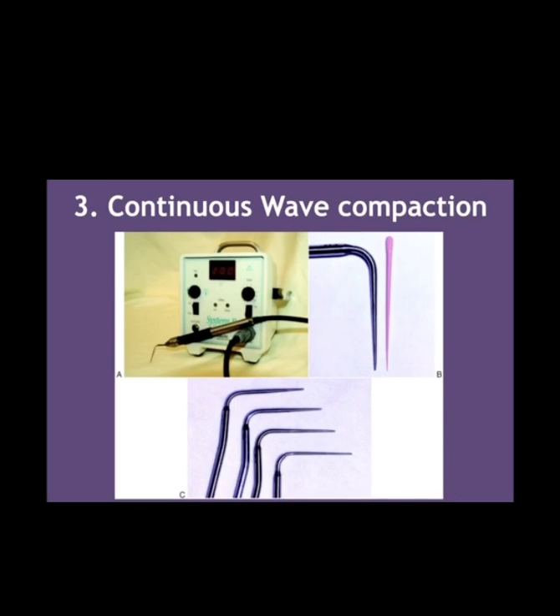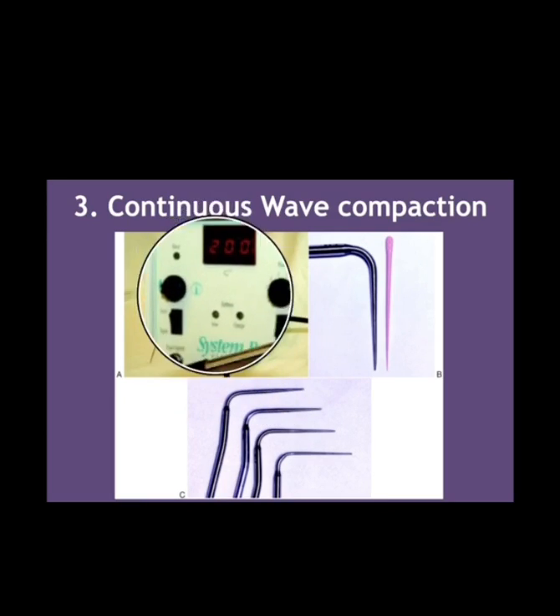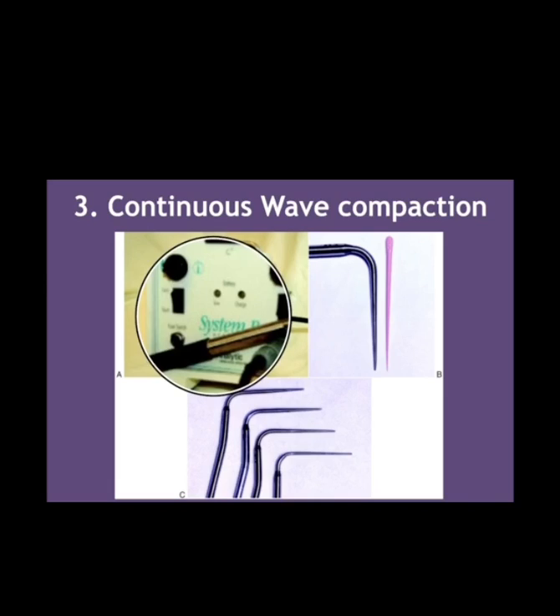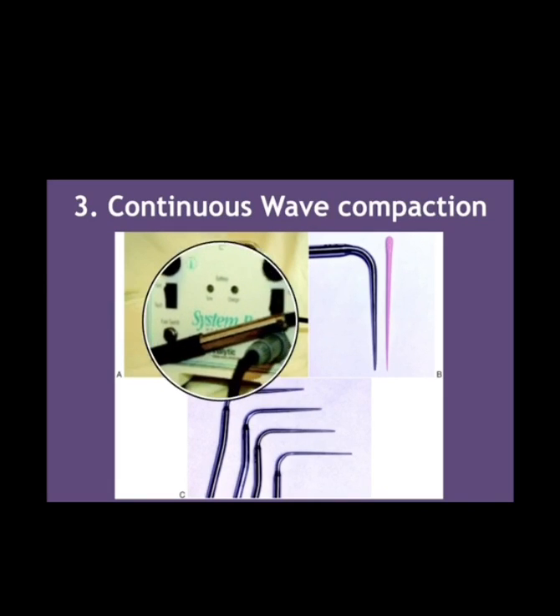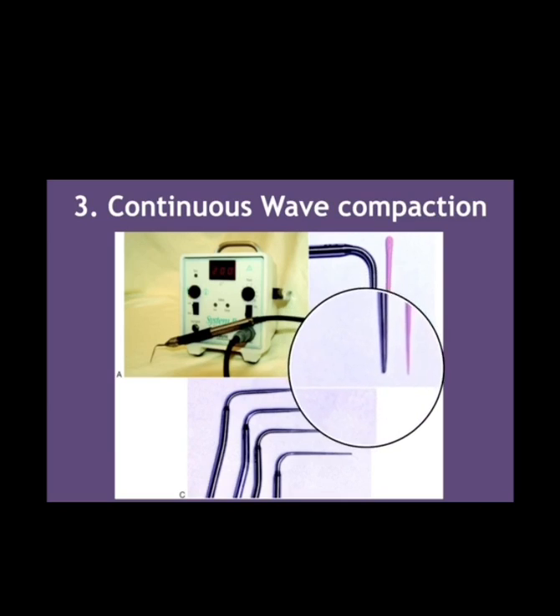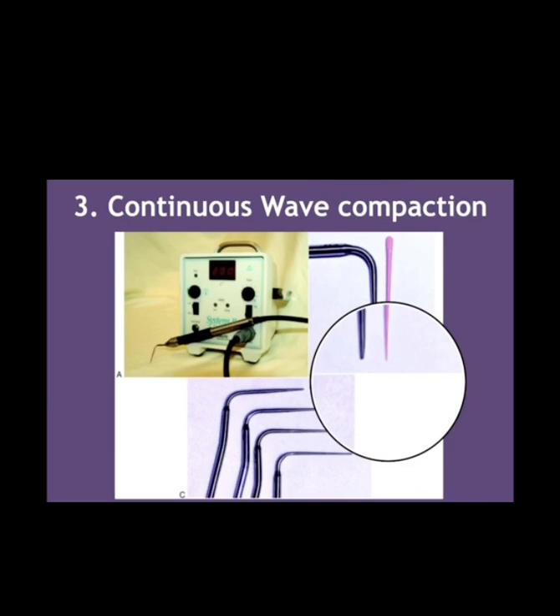length. Then for the continuous wave compaction technique, you also test your master cone to fit inside, and then there's a device known as System B, not Obtura. I'm sorry, it's System B, and it has pluggers like this part, and you choose the proper one, which is the one that reaches 3, 4, or 5 millimeters shorter than the working length when the canal is empty. Then you put the gutta percha inside, and when you put the gutta percha inside, you just push here, and when you put your hand here, it initiates heat immediately, and then you go inside the canal until the depth you need.